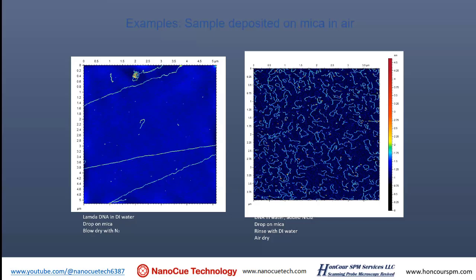You need to have the water extremely clean. The water cannot even touch anything. Right after the DI water machine, you use the cleanest glassware. The glassware has to be properly cleaned. And then you rinse the surface after you drop the DNA, and then you image. During the rinse, you wash away the excess DNA, and after that you blow it with dry air so that you accelerate its drying.